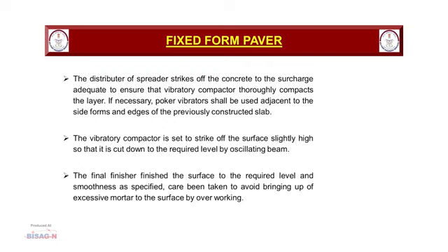The distributor of the spreader strikes off the concrete to a surcharge adequate to ensure that the vibratory compactor thoroughly compacts the layer. If necessary, poker vibrators shall be used adjacent to the side forms and edges of the previously constructed slab. The vibratory compactor is set to strike off the surface slightly high so that it is cut down to the required level by the oscillating beam. The final finisher finishes the surface to the required level and smoothens it as specified, care being taken to avoid bringing up excessive mortar to the surface by overworking.